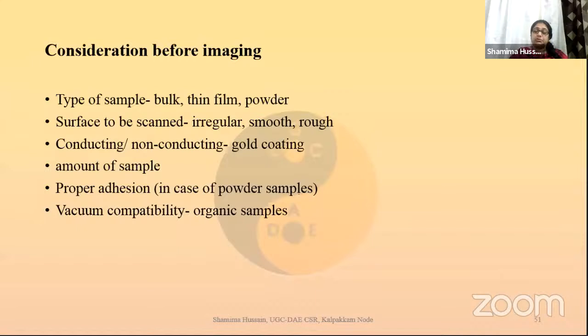And also, the most important part is this one, that you have to have the conducting surface. Now we are talking of electron microscopy where the probes are electrons. So this is very important that my sample surface is conducting. That means whatever electrons I'm shining on my sample, they need to have a path from the sample surface down to the ground. Otherwise, they will be residing on the sample surface. They will be giving you some kind of surface charge effect, which is going to hamper all the features, whatever we see. So what do we do?